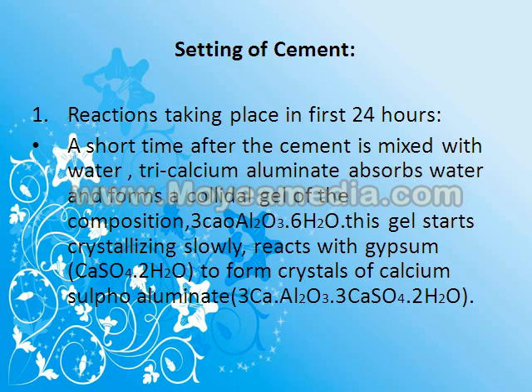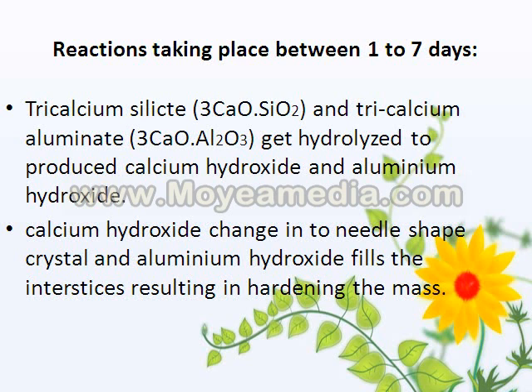Reactions taking place in 24 hours. A short time after the cement is mixed with water, tricalcium aluminate absorbs water and forms a colloidal gel of the composition 3CaO·Al2O3·6H2O. It is hydrated tricalcium aluminate. This gel starts crystallizing slowly and reacts with gypsum to form crystals of calcium sulfoaluminate.